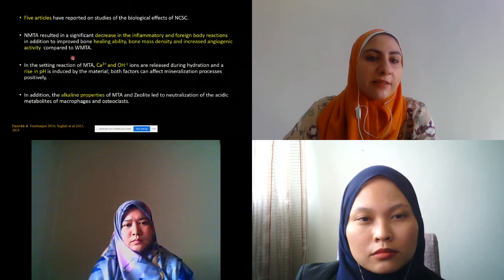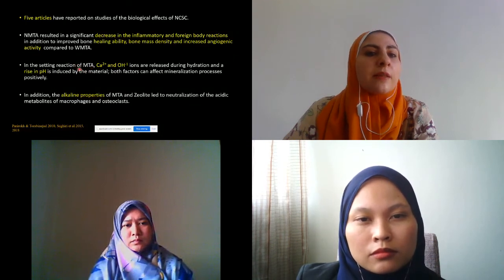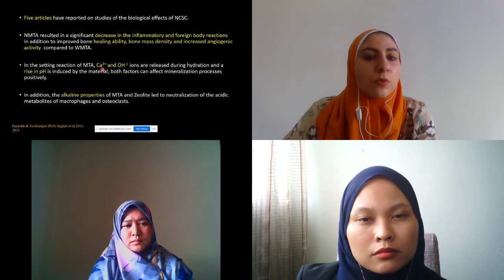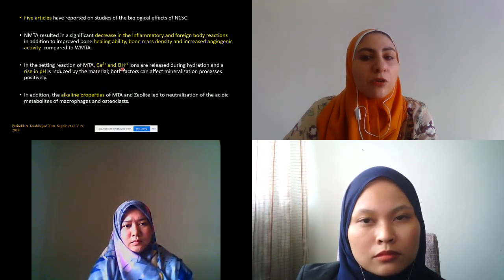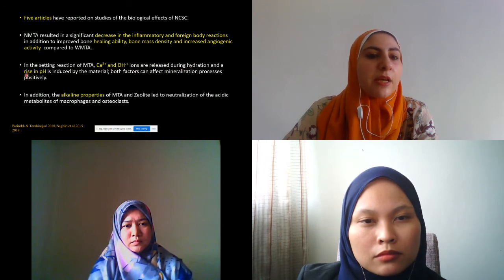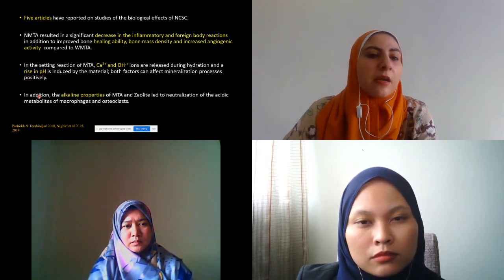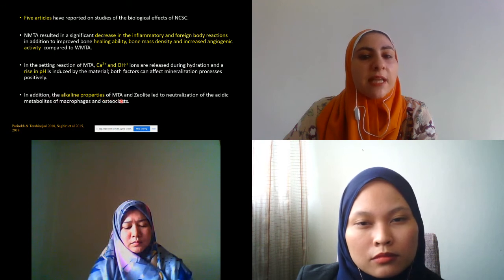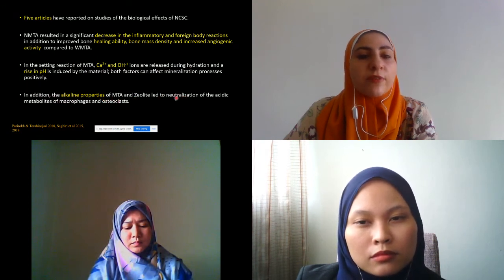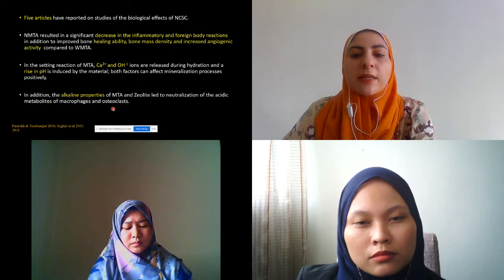Biological properties. 5 articles reported the biological properties of nanocalcium silicate cements. It showed that there was significant decrease in inflammatory and foreign body reactions. It improved bone healing ability, bone mass density, and increased angiogenic activity. This might be due to the setting reaction of Nano-MTA, which causes release of calcium and hydroxyl ions during hydration and causing rise in pH. In addition, the alkaline properties of MTA and zeolite lead to neutralization of the acidic metabolites of macrophages and osteoclasts.